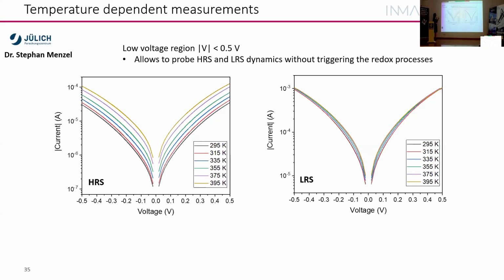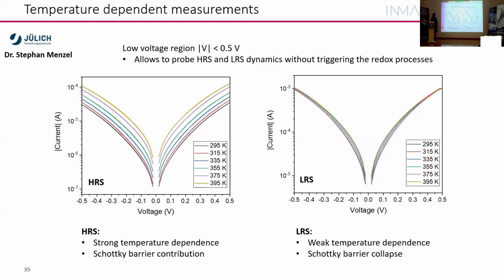What we also tried to do is to analyze not when it's switching, but really in the high and in the low resistance state. So we measured at these different temperatures. We did between 295 and 395 Kelvin, and we did these smaller IV curves, but it means you're in the same state, you're not changing the state, you're in the high or in the low state. And we saw that for the high resistance state, there's a strong temperature dependence, which we think is associated to the Schottky barrier contribution, while for the low resistance state, there's a very weak temperature dependence. So we think this Schottky barrier has collapsed.